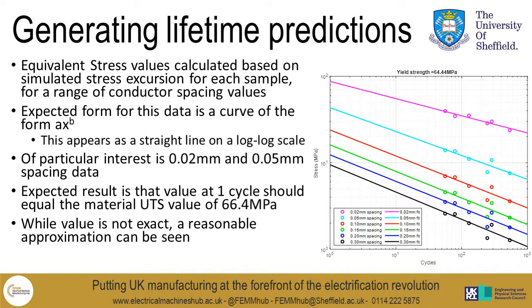This equivalent stress can then be plotted on the graph shown to the right alongside the experimental scaled cycles values. The expected form of this data nominally should follow the form of a x to the b, which on the log-log scale of that plot should appear as a straight line. The fitted values have been calculated and are shown on that slide as well.